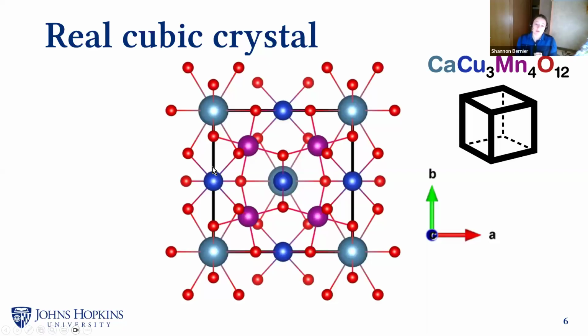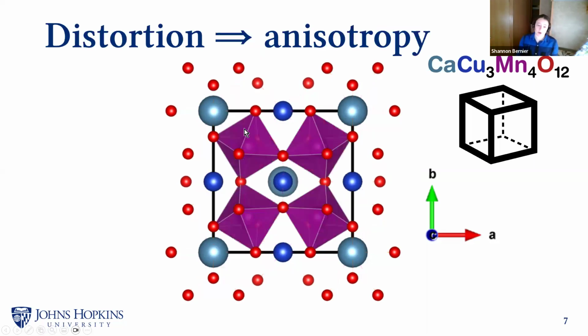Now, if I were looking specifically at a manganese atom here and the oxygen atoms that are bound to it, and I wanted to know if all of those oxygen atoms are in the same types of environments, in other words, if they're the same distance away from the central atom, it's not quite so easy to see in this particular picture. And so we frequently also use this representation, which is the coordination polyhedron representation. These are polyhedra that are drawn around a central atom, and the vertices are the locations of the atoms that are bound to that central atom. So using this, it's very easy to visually see that all of the oxygens are the same distance apart, because the polyhedron is really symmetrical.